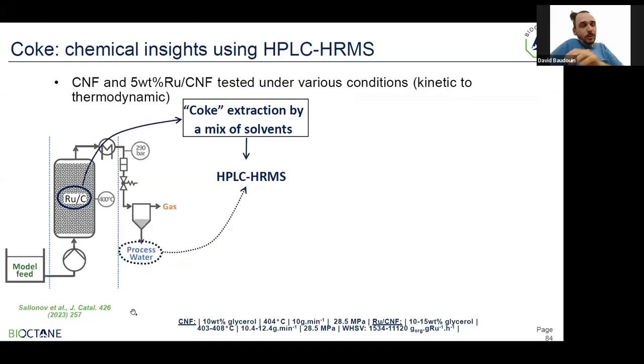So moving back to the setup that I presented earlier, we performed different tests at different conditions. We performed tests at thermodynamic conditions, so full conversion of the feedstock. We've also performed tests in the kinetic regime, so below 20% conversion, and also some intermediate conditions. We collected the spent catalyst and extracted the organic matter that deposited on the catalyst bed. This extraction was done with a mix of solvents that is very efficient at dissolving heavy carbons and particularly aromatic carbons. And these extracts were analyzed by HPLC HRMS.